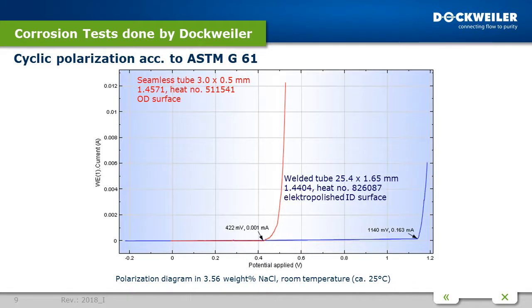The polarisation diagram comparing a seamless metallic bright-finished tube and an electro-polished ID surface of a welded tube shows the influence of electro-polishing clearly. The typical CPP value is around 400 millivolts for metallic bright surfaces; when electro-polished, we consistently measure CPP values of around 1,000 millivolts or better. When surfaces are pickled, the CPP value is around 500 millivolts, and when anodically cleaned, around 800 millivolts. We take two measurements per sample to avoid influences from single surface defects or incorrect sample preparation.